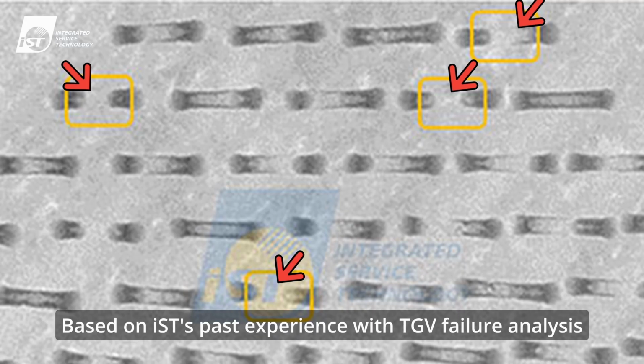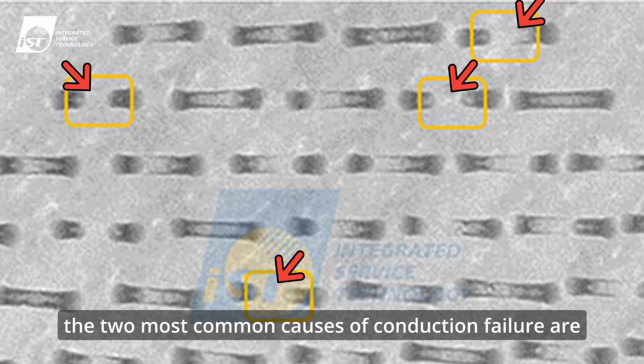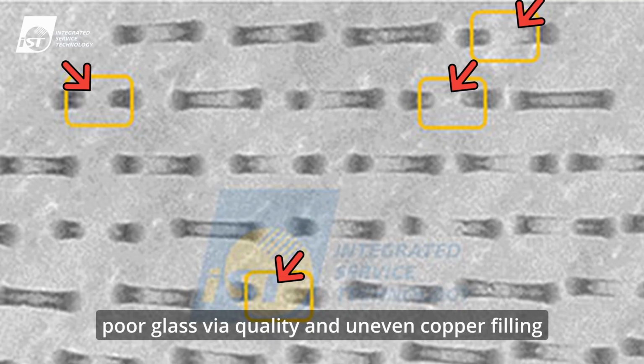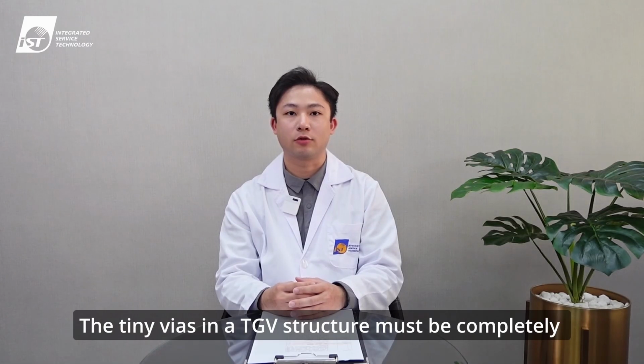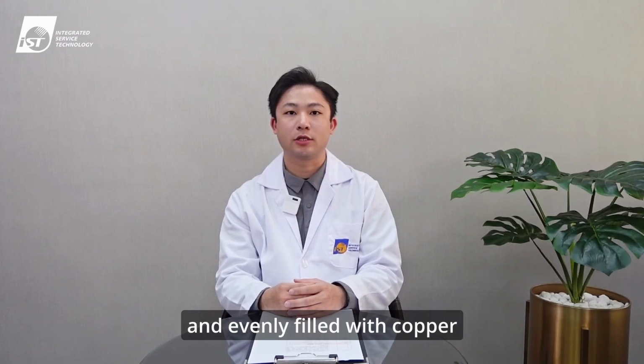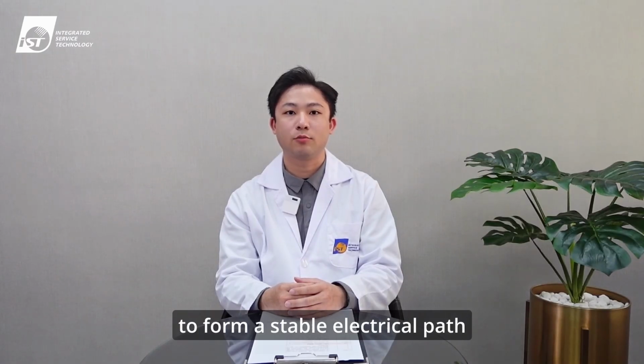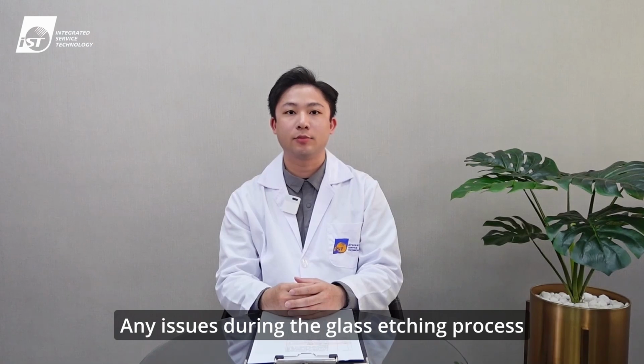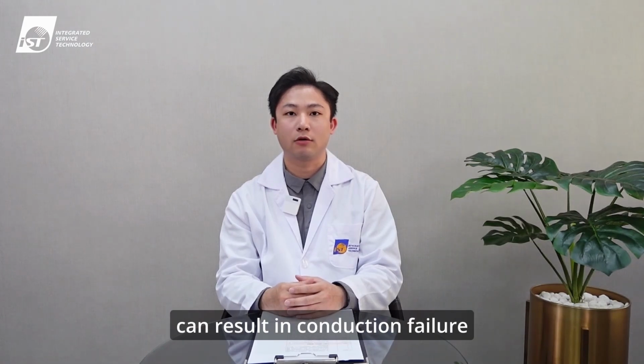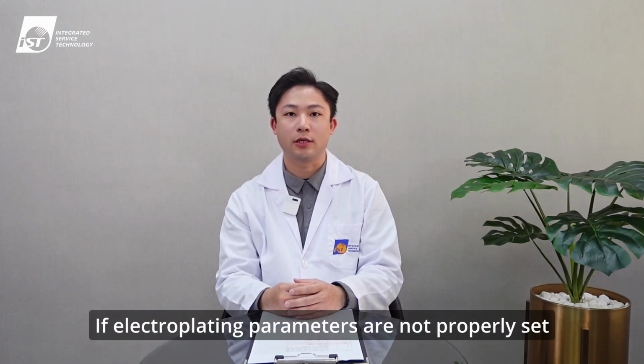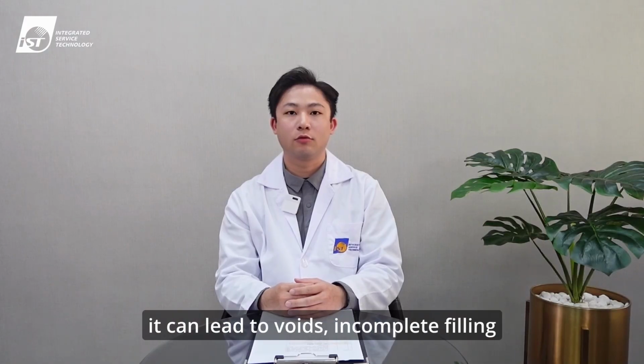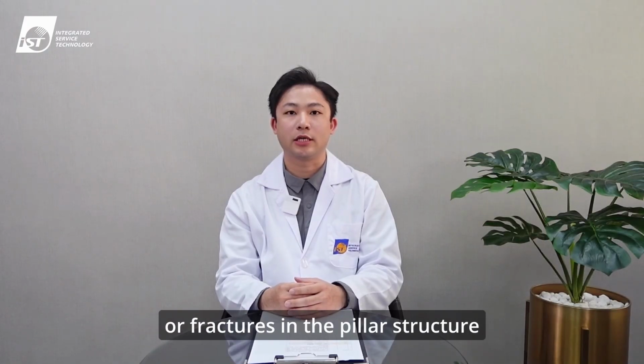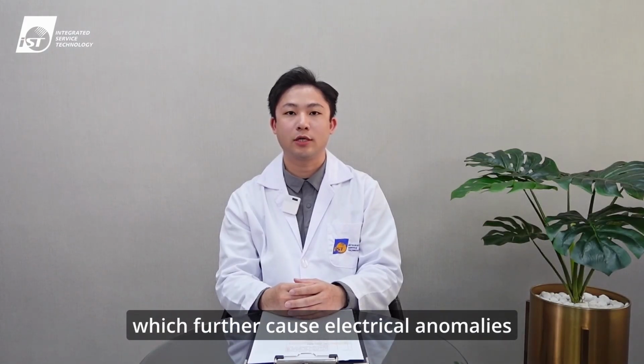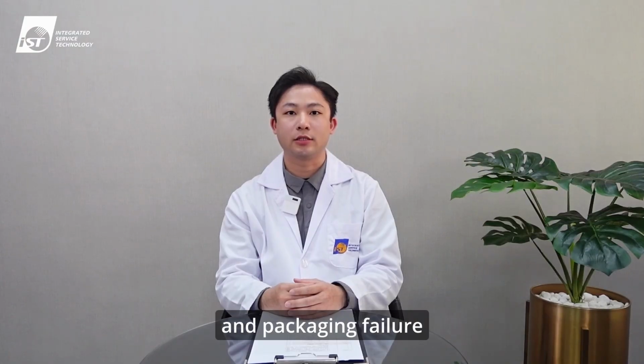Based on our past experience with TGV failure analysis, the two most common causes of conduction failure are poor glass via quality and uneven copper fill. The tiny vias in a TGV structure must be completely and evenly filled with copper to form a stable electrical path. Any issues during the glass etching process can result in conduction failure. If electroplating parameters are not properly set, it can lead to voids, incomplete filling, or fractures in the pillar structure, which further cause electrical anomalies and packaging failure.